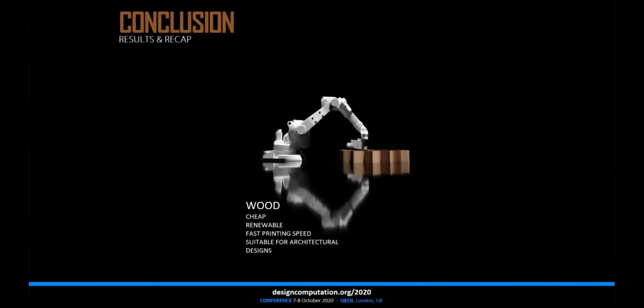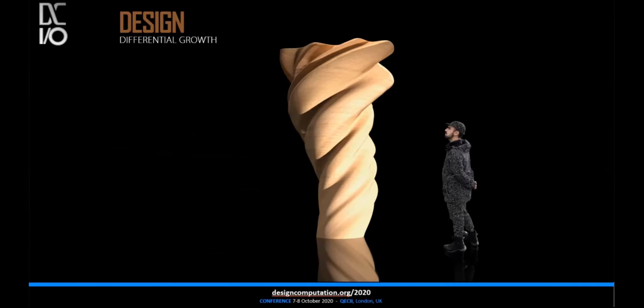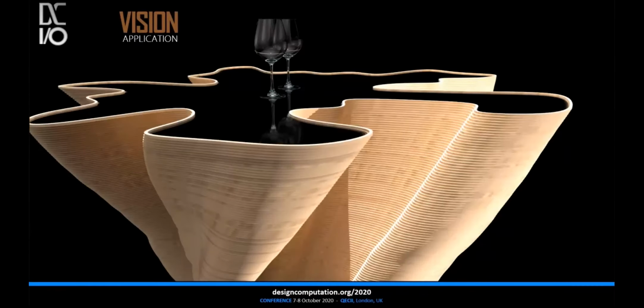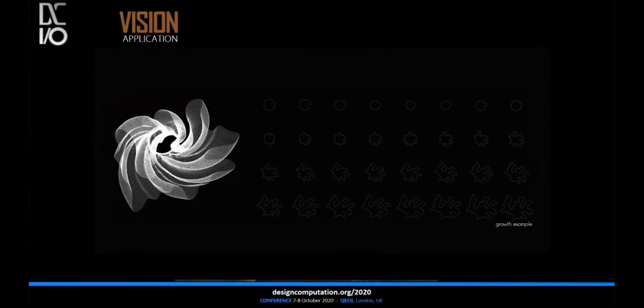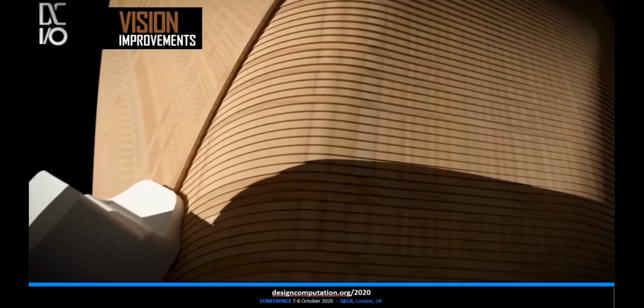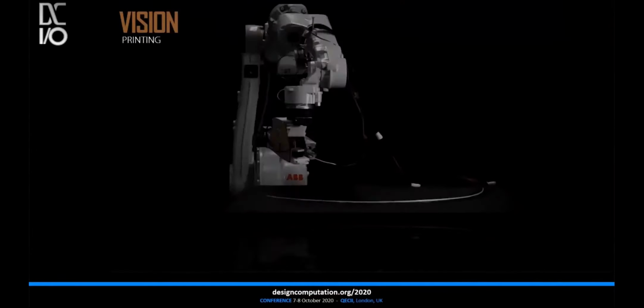However, the main trade-off between this new and the traditional techniques is the limitation in printing in a smaller scale. Considering the filament scale, the maximum printable radius of curvature is very acceptable for architectural and furniture scales. The overall printing strength highly depends on the filament surface finish after its treatment and the glue lamination. This behavior occurs in traditional 3-dimensional printing as well. By adding infill or additional perimeter shells, greater overall strength can be reached. An additional orthogonal printing layer on the outer shell can be considered. With this layer combination, the design strength can be greatly improved, especially in its layer adhesion direction.